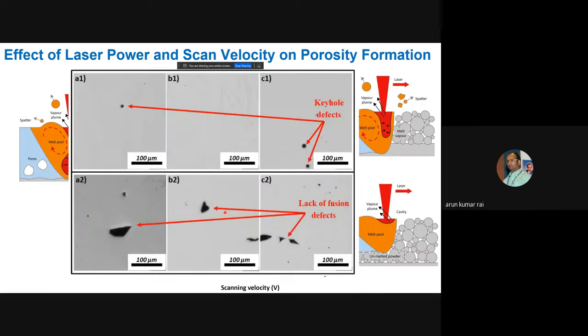So now I will show you how you can say that the material has the keyhole porosity formation or lack of fusion defect. If the pore shape you see in the optical microscope or SEM is spherical in nature, you can simply say this is due to entrapment of the gas and basically a high power you have used. So it is a keyhole mode based porosity formation.